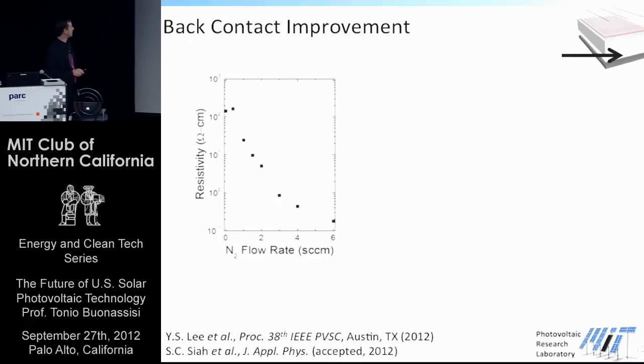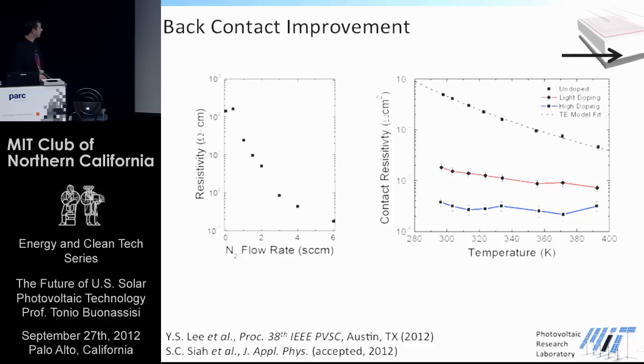Back contact, right back here. So marching right along, we have the absorber material. Check, we can knock that one off our list. How do we improve the back contact? For those people working with integrated circuits in the audience, you'll know that creating a good tunneling junction requires manipulating the resistivity of the bulk material. We can achieve that, modifying resistivity over three orders of magnitude, recently published at a solar conference. And with low resistivity material, now we can drop the contact resistance. In other words, the resistance necessary to extract the charge from the material to the point where it no longer impedes device performance. And this work is out for publication any day now.